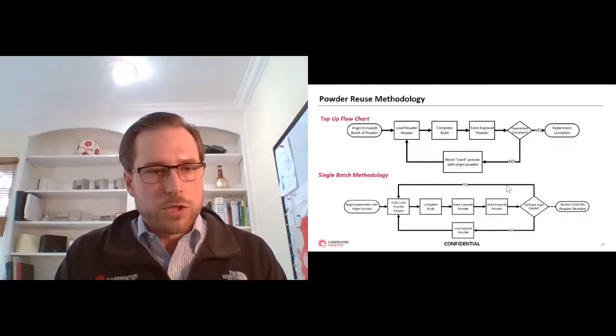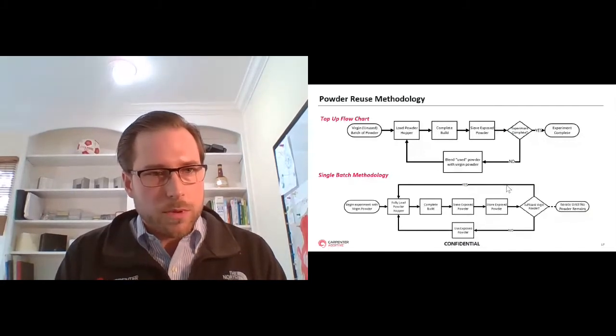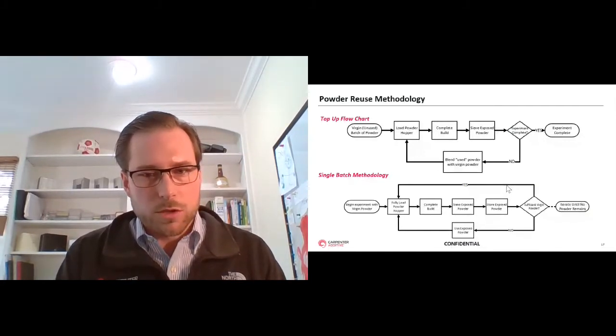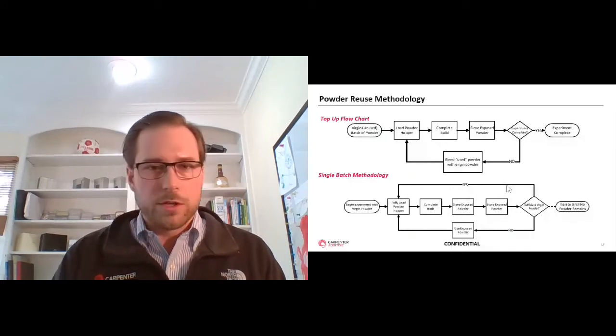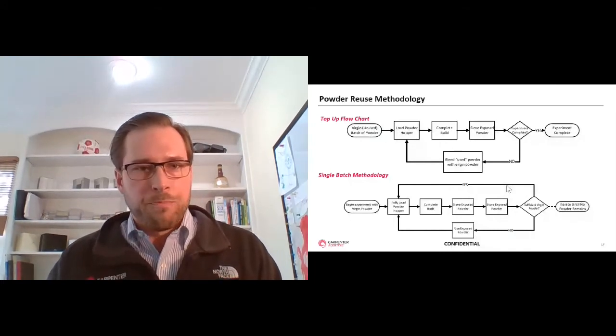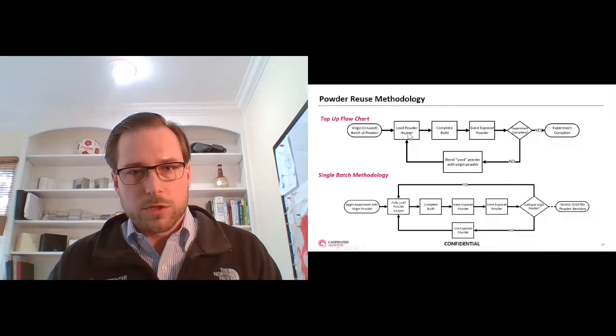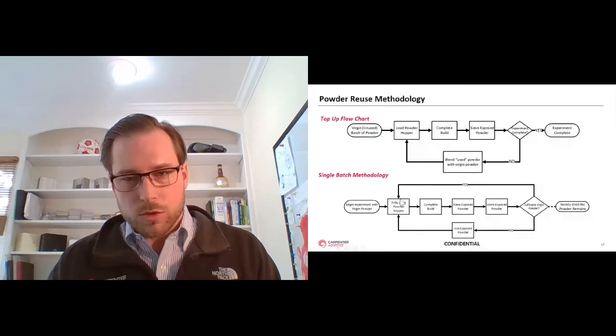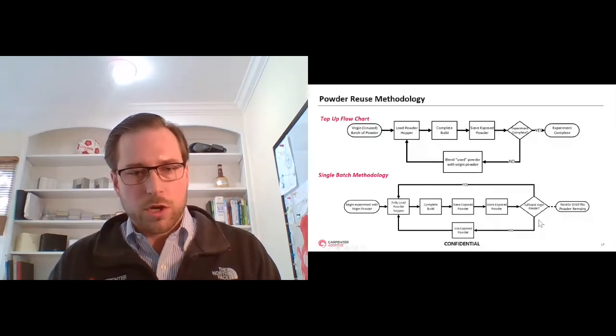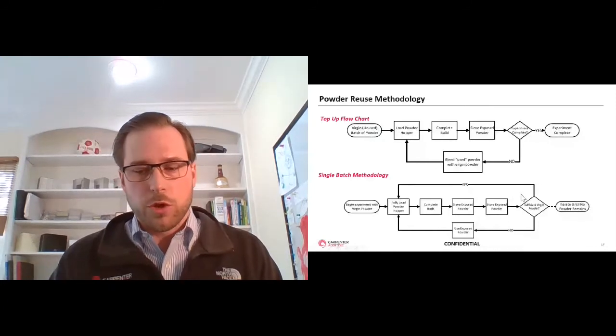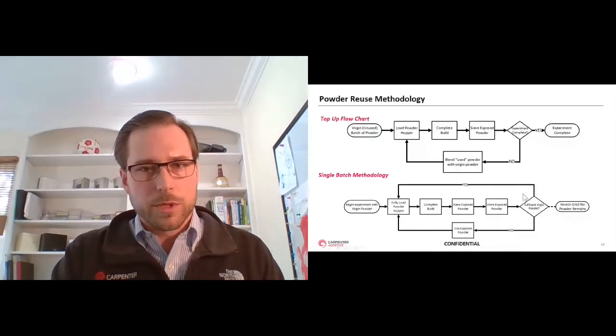So here are the flow charts that show the top up and the single batch methodology. The real change in the first one being that after you've completed the build cycle, you blend in the used powder with some virgin powder to reload into the machine, whereas in the single batch, like we talked about before, you just recycle the exposed powder with no additions of powder until you don't have enough powder left to do the build.